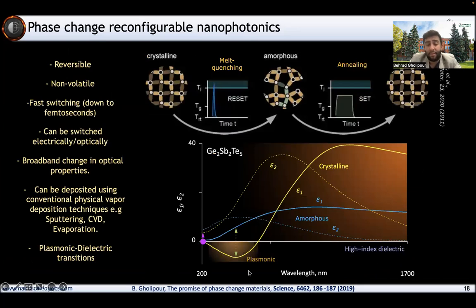Across much of the telecom and the visible band, this induces huge amounts of optical change. So you can see here, between amorphous being in blue and crystalline being in yellow, we have a large change in the visible and a much larger change in the infrared telecom band of the spectrum. And you can see, for example, very peculiar, this is the only material system that can switch between a plasmonic and a dielectric response across the visible band. This basically means that this material system, in this particular case, the alloy I'm showing you is germanium antimony telluride, GST, very common material used in industry.